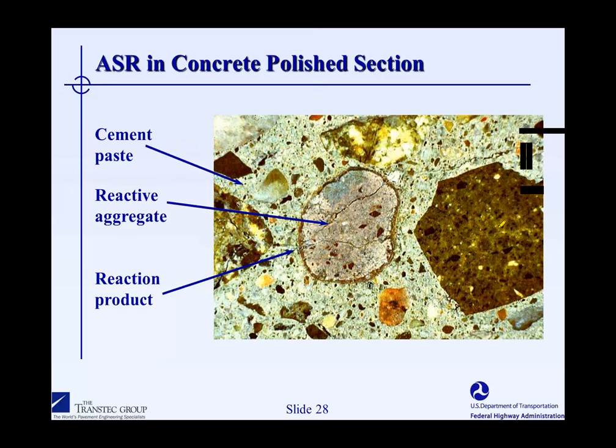This is now showing a polished sample at lower magnification. Now we're looking in reflected light. We have a thick chunk of concrete, so it won't transmit light. But we have a similar situation that we can observe at lower magnification. This is a reactive aggregate particle here, volcanic glass or rhyolite. And you can see that internally it's cracked within the aggregate.